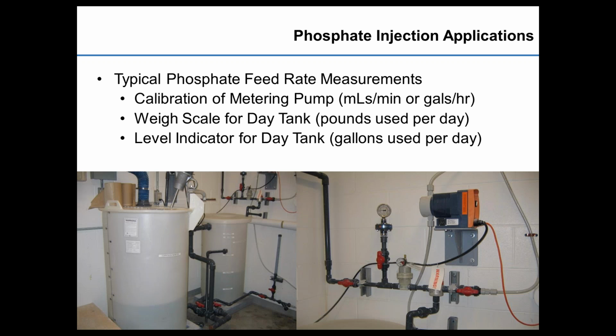Typical things that we would like to see a customer measure on a daily basis, and most states would require a plant to do these: we would love to see a calibration of the metering pump in mils per minute or gallons per hour, or, if the tank's on a weigh scale, how many pounds of product you used per day, or have a level indicator on the day tank and the bulk tank for how many gallons were used per day. All this information is critical because you can take it to see how much phosphate you're applying to the drinking water and what should be the associated dose of phosphate that you can measure in the distribution system, and make sure that those numbers add up and make sense for the system.